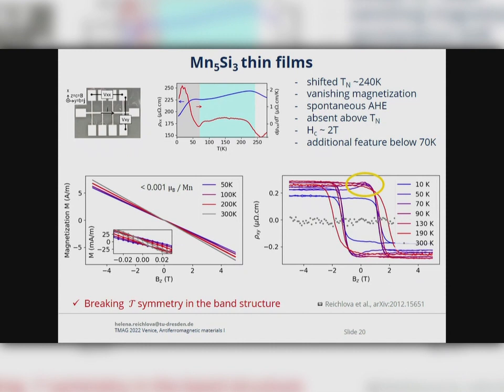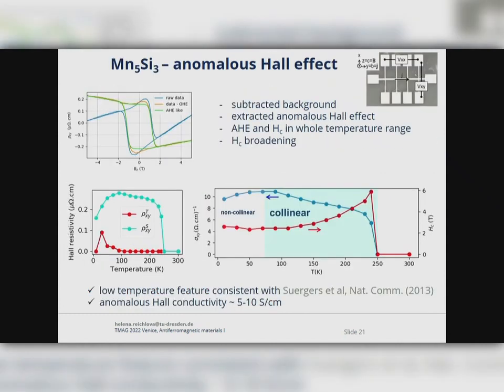And now I want to look a little bit more in detail at our measured data. Already here one can see that there is a feature which can be associated with the low temperature phase. And how do we actually get this feature out? We simply take our raw data, exactly as we measure it. We subtract the ordinary Hall effect, and then we extract the anomalous Hall effect, and the remaining part I call here rho XYT. And this is indeed present only in the low temperature phase, and it's also consistent even in the amplitude with Suergers and his polycrystalline films.